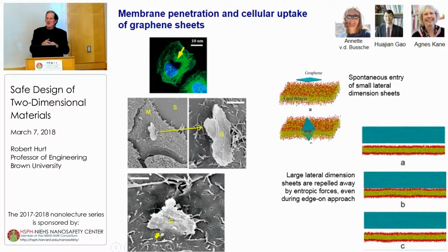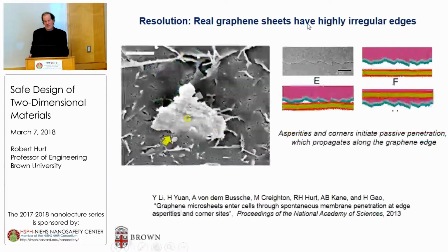And Huajian Gao does molecular mechanics modeling and nanomechanics modeling. And so he put very small graphene layers above these coarse-grained simulations. These are full membrane molecular dynamics simulations, and these little graphene sheets dip in readily. But if you take a large sheet and you try to bring it to the membrane and cut it, and the membrane's undulating and oscillating, you cannot, with low energy barrier, penetrate that membrane. They're repelled away as the membrane undulates. And it's kind of a problem because the data shows that these flakes enter, but the simulation shows that they can't. So that sounds like it doesn't make a great publication.